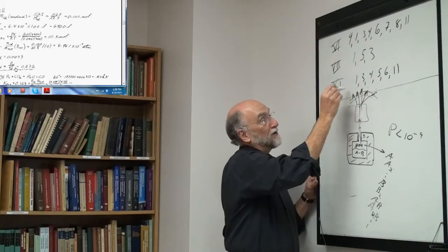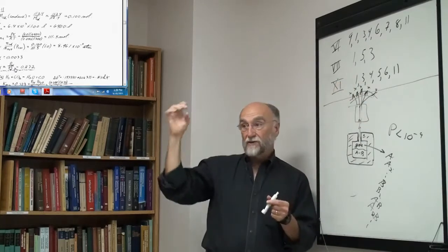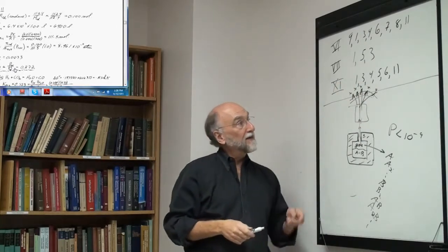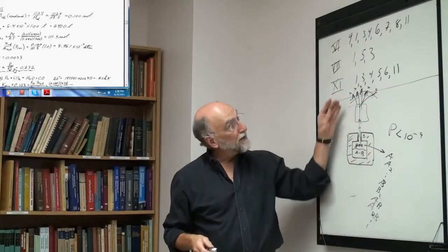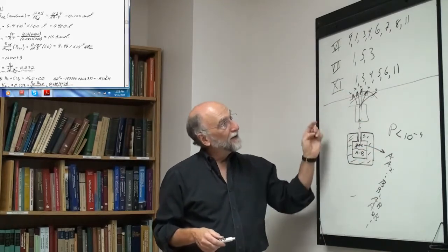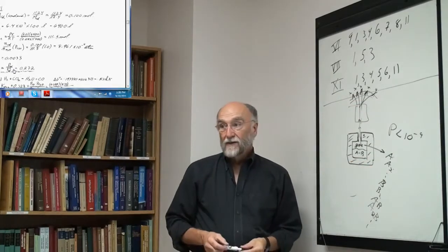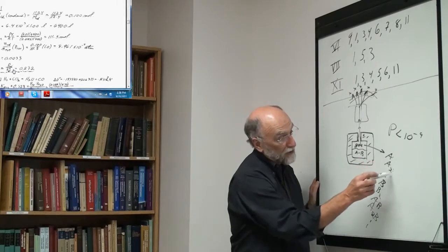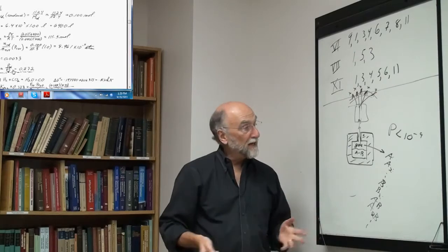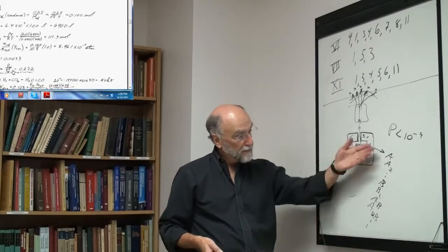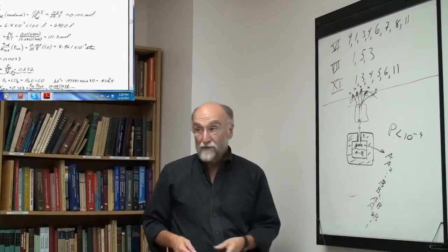You move your counter around, and you can get how many molecules per second of each of the different molecules there are. So you separate the gas and you can get the number of molecules per second of each different kind of gas, and from the angle that they were bent because of the magnetic field, you can work out their mass, so you figure out what they are. So what you end up with is the partial pressure of every single molecule, which is exactly what you want. Then you can calculate the activities of A and B, because you know how much there is of everything in there.